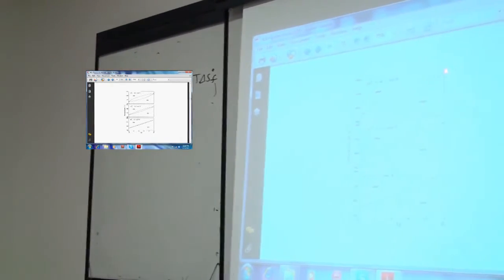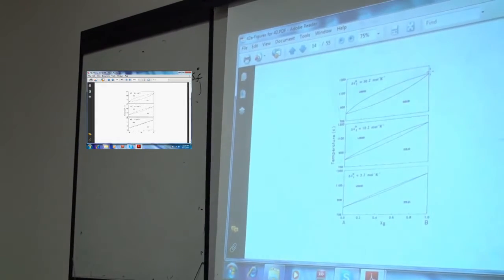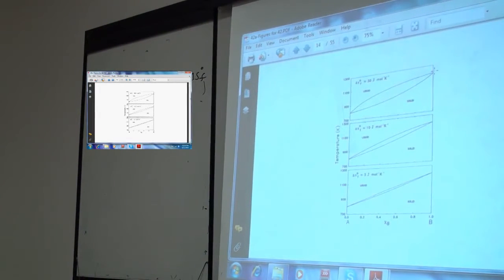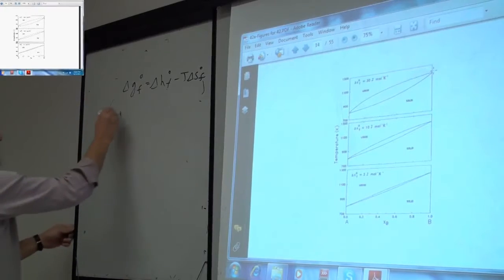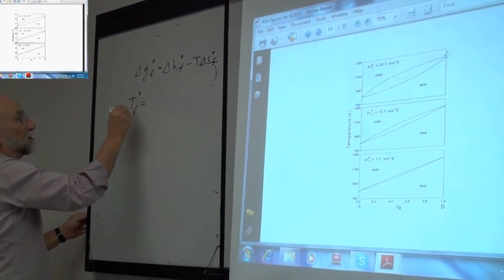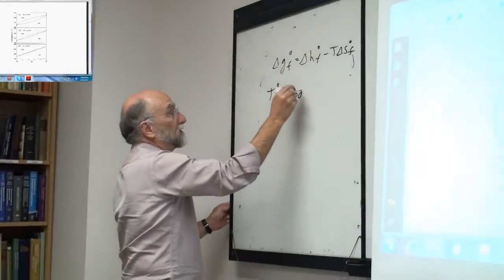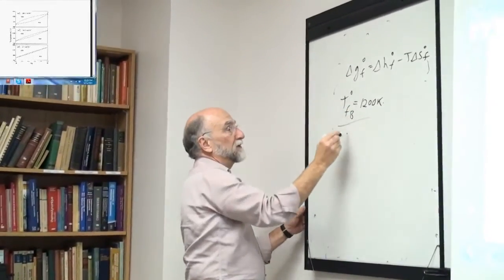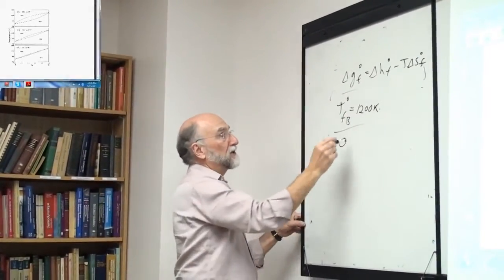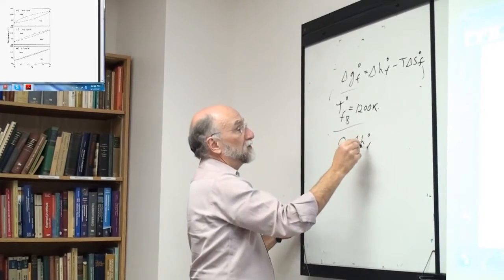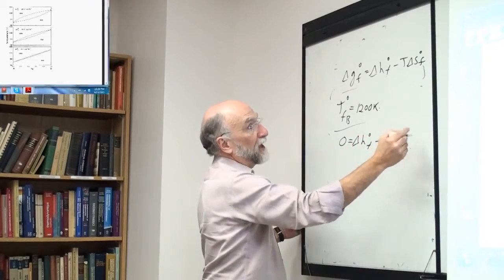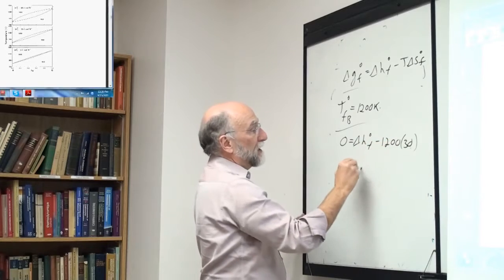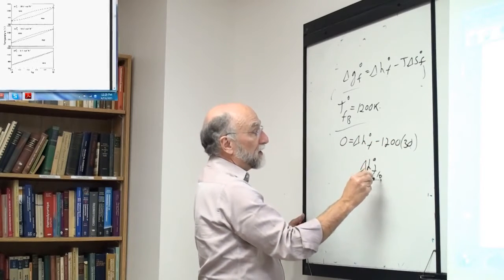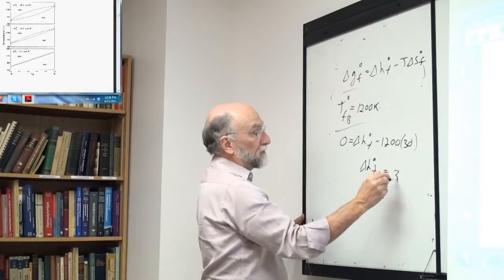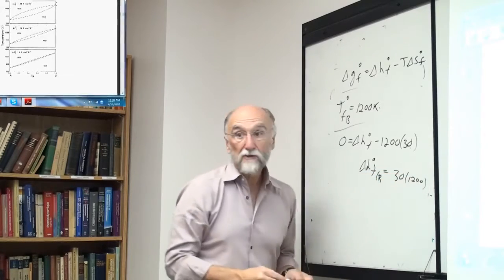Okay, so if it's equal to 30, and if the melting point of B is equal to 1200 K, then at the melting point, the Gibbs energy of fusion is 0, and that's equal to the heat of fusion minus 1200 times, in the top panel, 30, and so the heat of fusion of B then is equal to 30 times 1200 and so on.